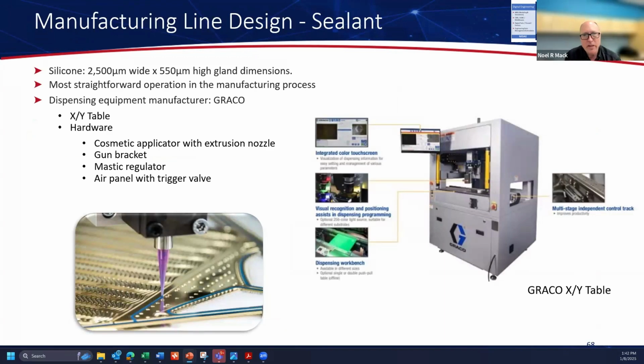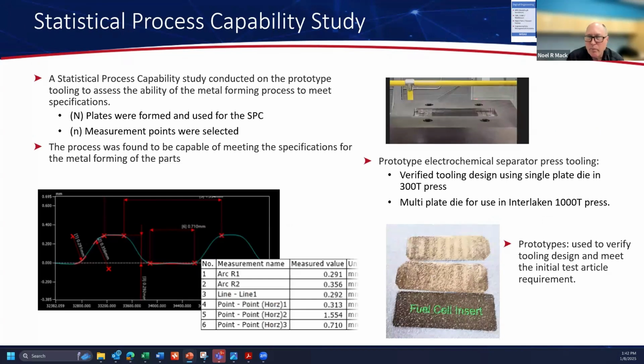Here's just looking at the silicon bead going down with an XY table, really using a cosmetic applicator with an extrusion nozzle, and then a mastic regulator, and then a trigger valve to actuate it. On the V&V side, we've done the relevant SPC studies to know that we can form plates, and not just form one, not just form a couple hundred, but get to full production rate. So we ran X number of plates through the system, did the appropriate measurements, and tuned in the forming parameters to match the simulation to be able to get to the capabilities that we need.